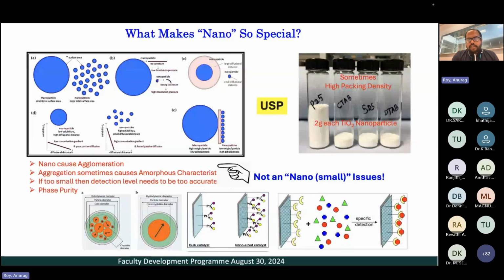So, what makes nano so special? As I mentioned, any material which comes to the nano form changes its properties drastically. Here is an example you can see. 2 gram each of TiO2 nanoparticles, distributed in 4 bottles, and interestingly, there is high packing density. This is the standard bulk TiO2, and this is the nano TiO2. Each is 2 gram, but their packing density is so high. And when it comes to the nanomaterial, using CTAB, SDS, DTAB, different chemical synthesis that we applied to develop a nanoparticle, that causes the high packing density.